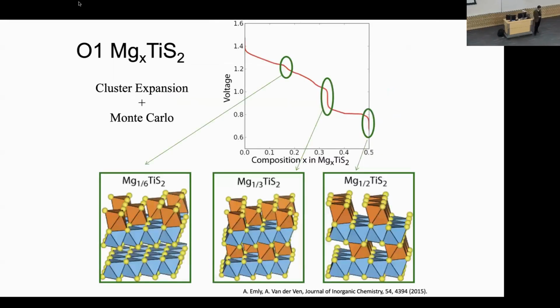When you do magnesium, you get a voltage curve like this. Here, you get all these little steps, and they're pretty pronounced. Each step corresponds to an ordering of magnesium and vacancies. The reason these are so stable is that magnesium is 2+, so you have very strong electrostatic interactions, much stronger than between lithium. So the in-plane interactions between magnesium are much stronger, and that leads to pronounced ordered phases at these stoichiometric compositions, like 1/6, where you have the staged phase, 1/3, or 1/2, where you get these rows. And each one translates into a voltage step.